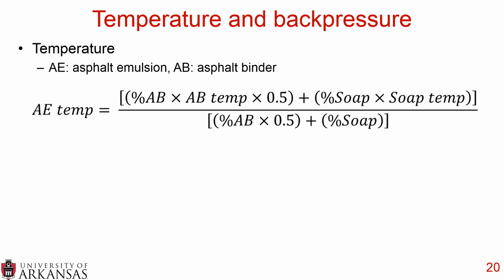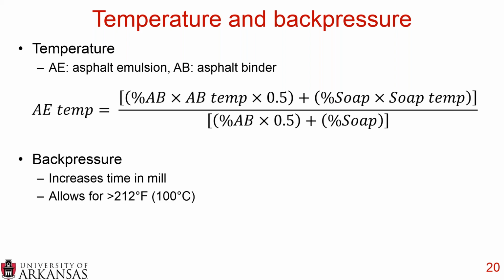But the asphalt emulsion temperature can be calculated by multiplying the percent asphalt binder by the temperature of the asphalt binder times 1/2. You add that to the percent soap solution times the soap temperature, and you divide it by the percent asphalt binder times 1/2 plus the percent soap solution. And this is important because the temperature of the asphalt binder is critical to get the right viscosity. The temperature of the soap solution is critical because that feeds into the temperature of the asphalt emulsion. And you want to hit that proper temperature of asphalt emulsion to make sure you have a good product.